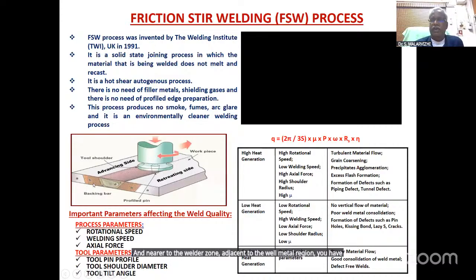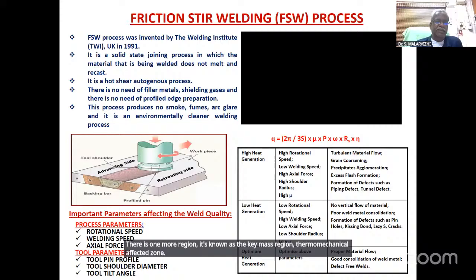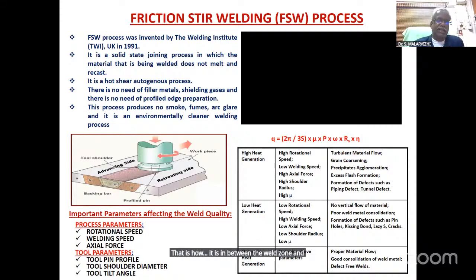One important typical characteristic feature of this process is that, like other welding processes, you have unaffected parent metal away from the weld zone, and nearer to the weld zone, adjacent to the weld metal region, you have the heat affected zone. This is true in all cases. But in this process, there is one more region known as the TMAZ, thermomechanically affected zone, between the weld zone and the HAZ. That is the typical characteristic feature of this process. The D region in this diagram is known as the stir zone, also called the dynamically recrystallized zone. Dynamic recrystallization takes place during welding and produces very fine grains in the stir zone region.